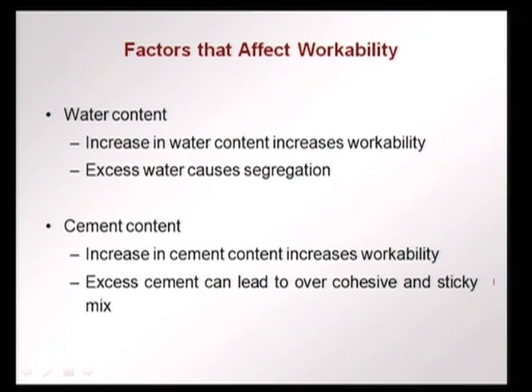So, even in self compacting concrete, which you saw in the earlier slide, which showed high flowing ability, you have limited water, because more water always leads to more segregation. So, water content helps in workability, but it is not something that we always use for getting the workability that we want. Increase in cement content increases workability, because more paste means the concrete can flow more easily. However, again excess cement paste can lead to over cohesive sticky mixes, not to talk about the additional cost. Shrinkage, thermal stresses will also increase when we have higher cement contents.